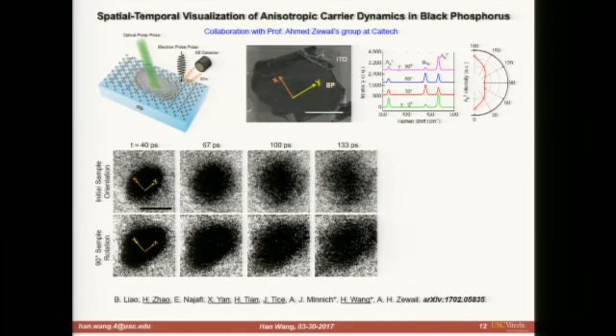We shine the pump laser, which comes at an angle, so you can see the spot is kind of elliptical because the laser comes from the side, and then it strikes the sample. What you're imaging is the secondary electrons collected from the secondary electron detectors, just like in the SEM imaging you usually do.